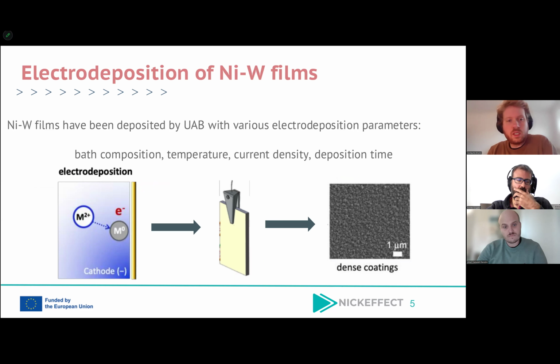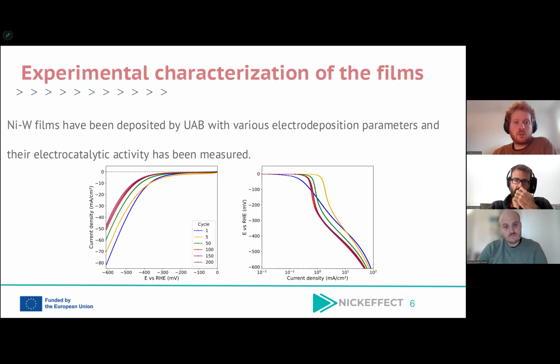So they were doing these experiments. They were depositing these films and measuring the electrocatalytic activity. And so we were getting these kinds of curves, the LSV, linear sweep voltammetry curves, so the current density versus the potential for different cycles. There were 200 cycles and we took 6 of them. This is really the raw output, these curves.